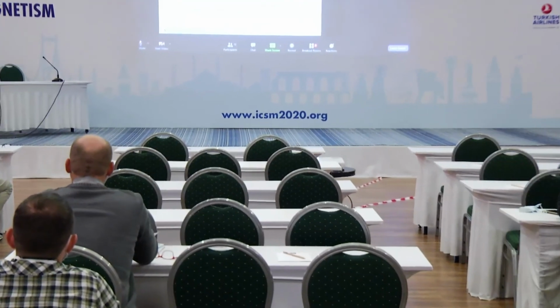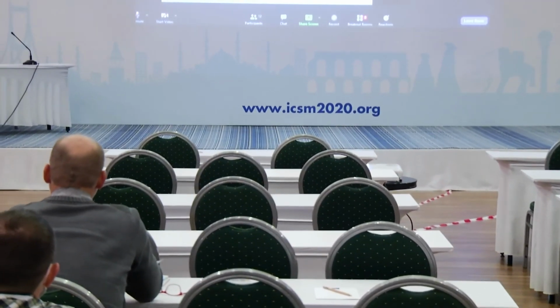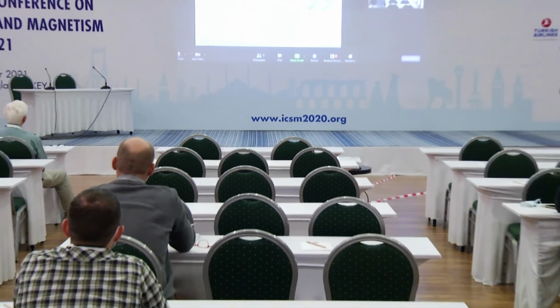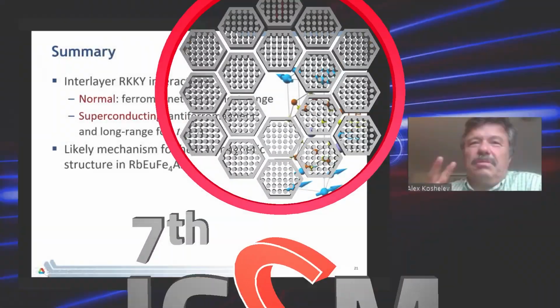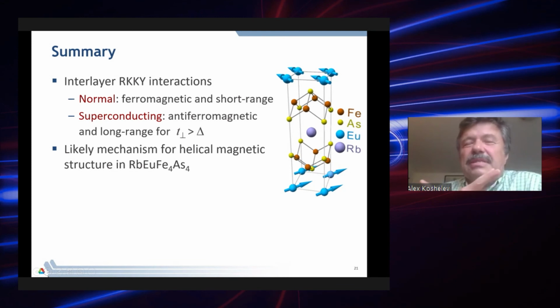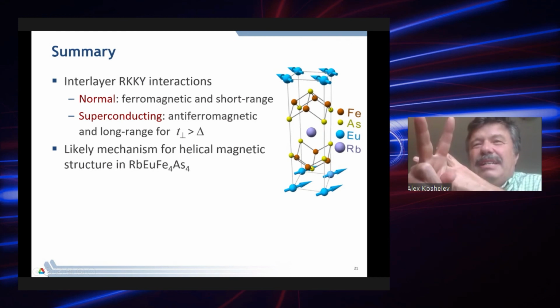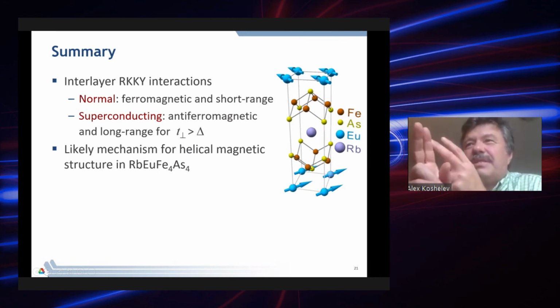So what would you expect for the helical structure if you apply a field parallel to the planes? A phase transition to a double periodic structure, where spins in two layers are tilted at one angle and spins in the other two layers are tilted at another angle. And eventually, of course, it should saturate at a certain field.